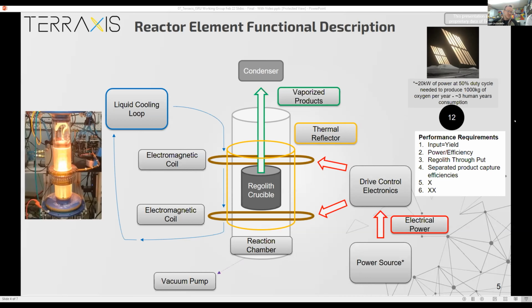Those coils wirelessly input power to the crucible directly, which then reaches the critical temperatures we need to begin disassociating the regolith. As the regolith is heated up to these critical temperatures and disassociates, those products released as vapor will then move out of the reaction chamber into a condenser assembly, where depending on the temperature in the condenser, different compounds will begin to condense back out from vapor phase to other phases. We have a pretty simple liquid cooling loop that we use here on the ground to maintain the unit at temperature. And because we're not on the moon, we don't have a natural vacuum to work with. We have to use a traditional vacuum pump.